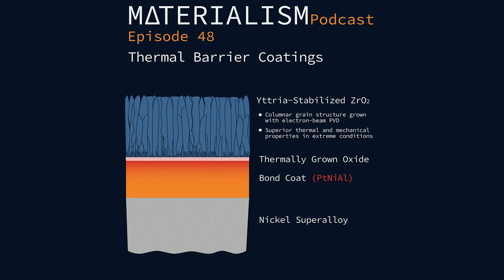If you look at it, there's been a lot of work. In fact, there forms a really cool microstructure. When you cycle these things over time and look at them to figure out maybe why it failed, when they actually harvested it and looked at it, they saw something really surprising. You've got the ceramic coating up top, the TBC layer, and then we expected to see a nice flat thermally grown oxide right under that, and then a nice flat bond coat layer and a nice flat metal underneath that. But instead, what they found is this undulating, rippling structure under there, which was pretty unique and in the early days hard to understand. So what was going on there, Andrew?